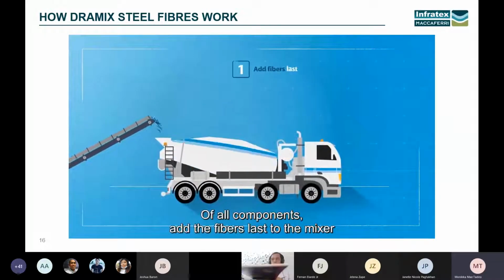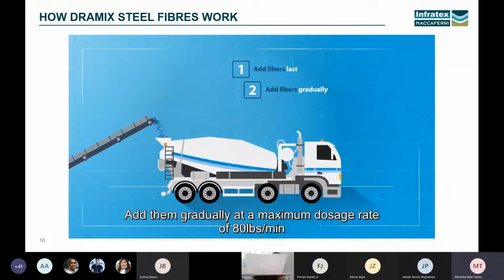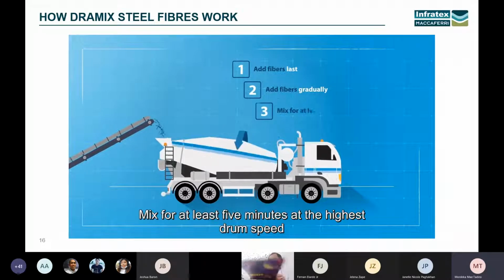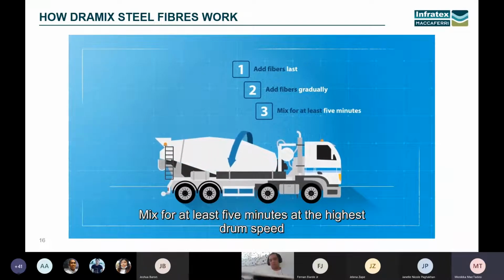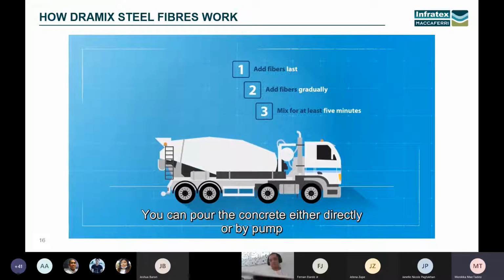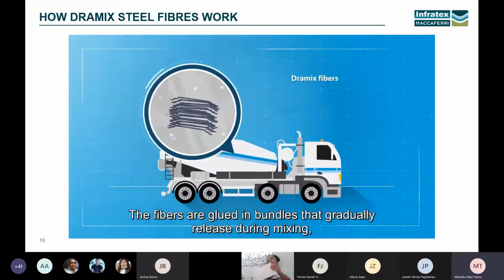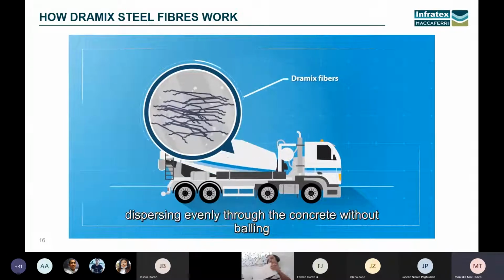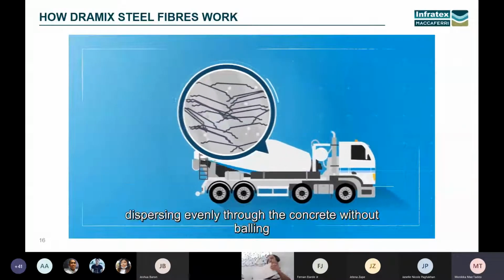Of all components, add the fibers last to the mixer. Add them gradually at a maximum dosage rate of 80 pounds per minute. Mix for at least 5 minutes at the highest drum speed. You can pour the concrete either directly or by pump. The fibers are glued in bundles that gradually release during mixing, dispersing evenly through the concrete without balling.